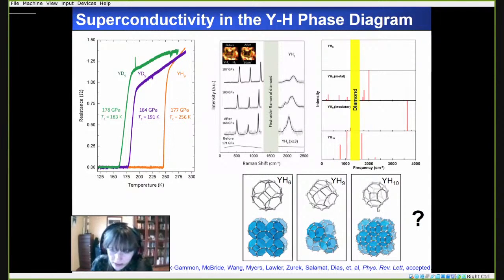So we computed the Raman spectra of these three clathrate phases, YH6, YH9, and YH10. And note that the Raman is taken within a diamond anvil cell. So there is a region where we do not see any peaks because they're obscured by those of the diamond.